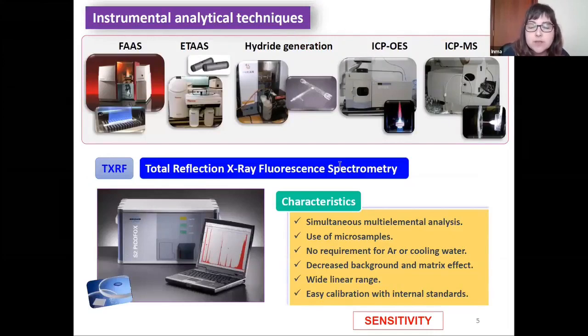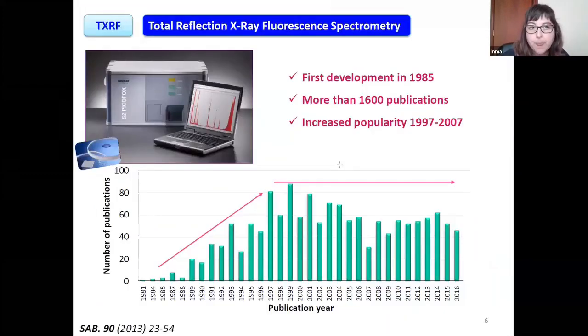The current analytical instrumentation allows the determination of elements at very low concentration. However, it is still often necessary to apply separation and preconcentration strategies prior to quantitative determination. For example, this is the case of TXRF, Total Reflection X-ray Fluorescence Spectrometry, that has several advantages, such as the simultaneous multi-elemental analysis, the suitability of dealing with microsamples without the requirement of argon or cooling water, with decreased background and matrix effects, wide linear range, and easy calibration. However, the sensitivity of this technique is an inconvenience to have under consideration. The development of TXRF was in 1985, with increasing popularity, becoming nowadays a well-established technique.